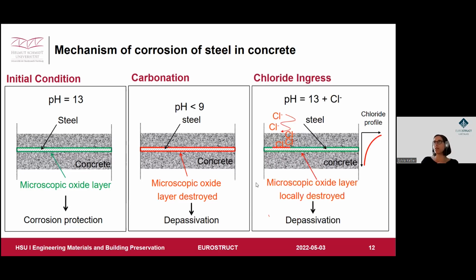So other boundary conditions have to be fulfilled. And for the more severe condition, we have concrete that is still in an alkaline condition, which is often forgotten. It's still alkaline. But we also have chlorides in our system, mostly from sodium chloride from marine environment or from de-icing salts. They penetrate through the concrete until a critical threshold has reached the reinforcement level, and there the microscopic oxide layer will be destroyed locally. So here we have the typical chloride corrosion, which also leads to the depassivation of the steel. All these processes will take time. This is something we can see in the 2D diagram as well.